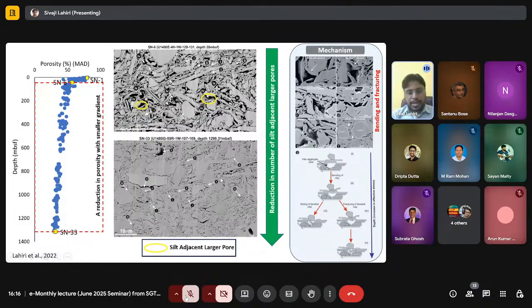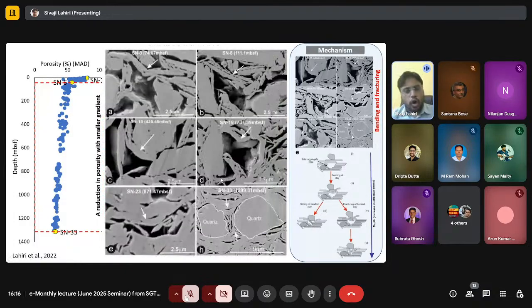Now, coming to the deformation mechanism, here in this depth range, we observed a very interesting deformation mechanism. So let's try to have a look at them. Here in this particular microstructure, you can see that there is a silt particle. Adjacent to that, there is a silt adjacent larger pore. On the top of that, you can observe there is a clay particle, and the clay particle actually got fractured. Now again, you observe there is a silt adjacent larger pore. On the top of that, there is a clay particle, and this clay particle actually got bent because of the compaction stress.